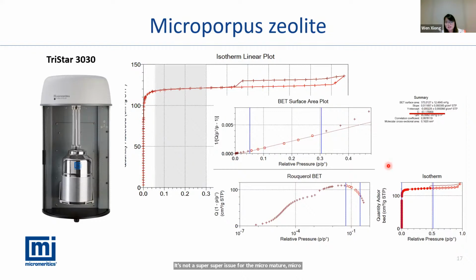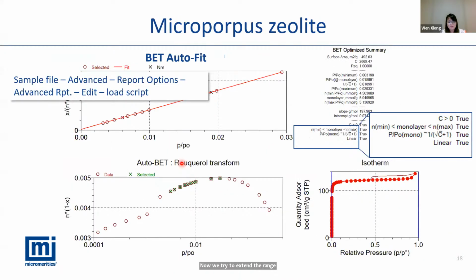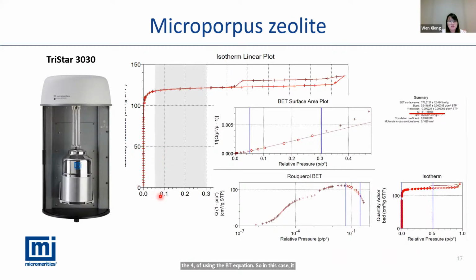Now we try to extend the range to a lower relative pressure. And then our software can offer auto BET fitting. This is for the Micromeritics software, the BET auto-fitting script. This script does the BET calculation automatically and checks all 4 criteria of using the BET equation. So in this case, when we are using the traditional relative pressure from 0.05 to 0.3, we get a negative C constant. So all this data reduction is incorrect.